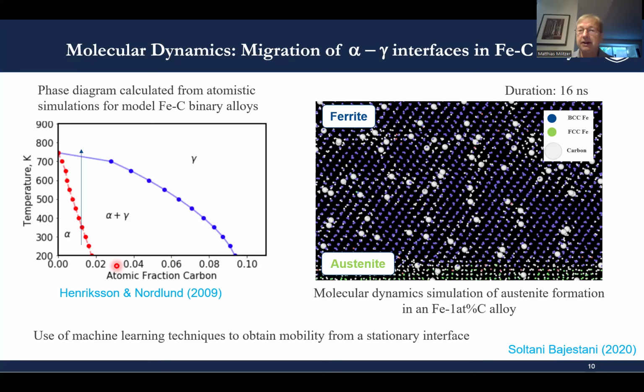We look here at an alpha-gamma interface in an iron-carbon alloy. And basically what we use is the potential of Henriksson and Nordlund that creates what looks like a reasonable iron-carbon phase diagram when we are considering the two-phase field austenite ferrite. If you look very carefully, the temperature scale is in Kelvin. Pure iron is predicted to have an equilibrium transformation temperature of about 750 Kelvin, which is much different from the actual transformation in pure iron. May this be as it may, maybe we can still learn something out of these simulations.